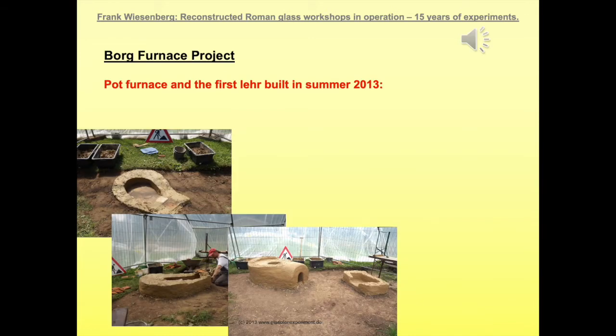Building this furnace reconstruction employed a lot of Roman roof tile fragments, which were actually from the excavation of the Villa Borg, which is still continuing today. So a lot of Roman roof tile fragments were available. The daub, which is used for the side walls and for everything else as building material, is actually from the site at Borg. So it's a very natural building material, probably used by Romans too. The building took a couple of months during summer 2013. Even during the building of the large furnace, I started reconstructing the lehr, which is located pretty close by.